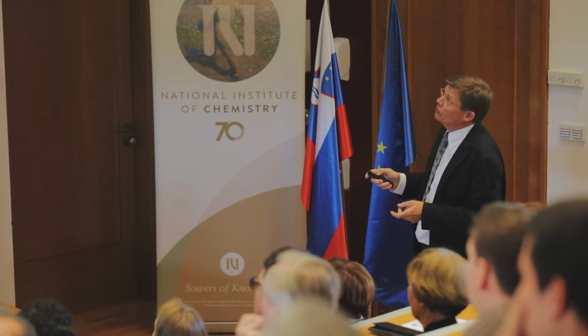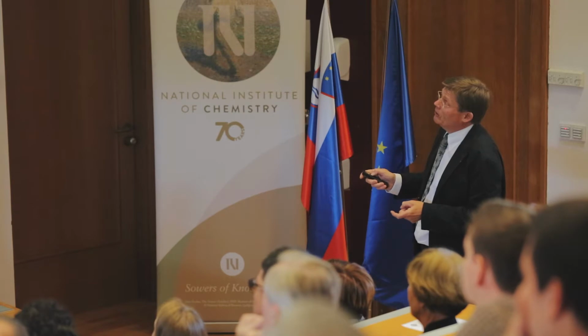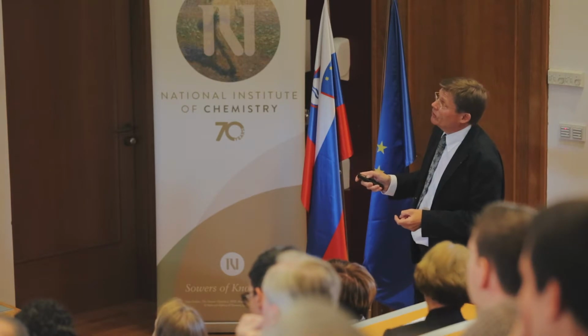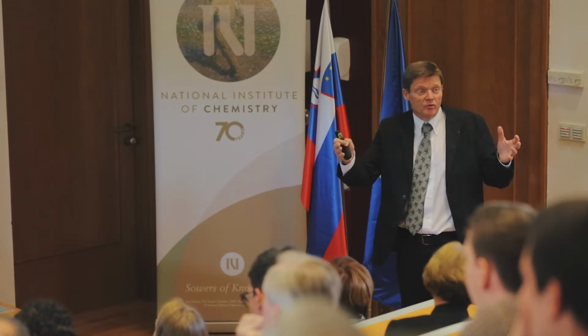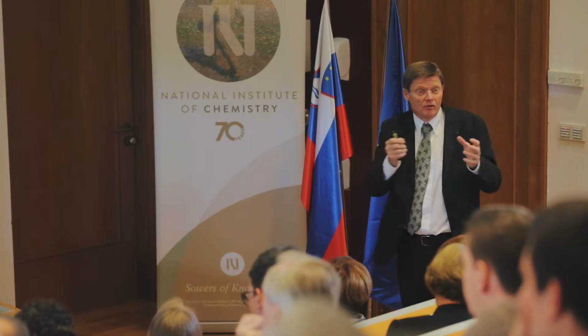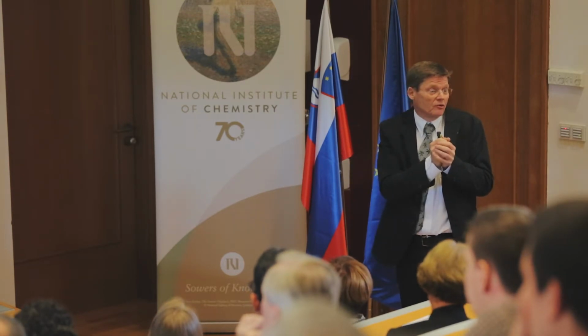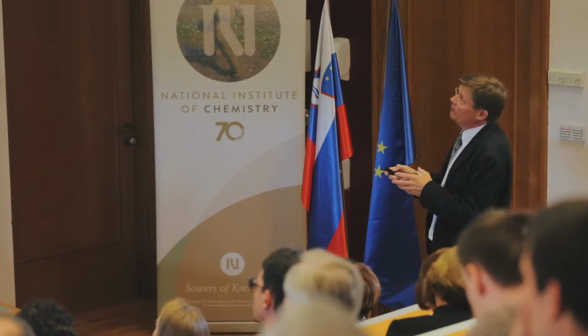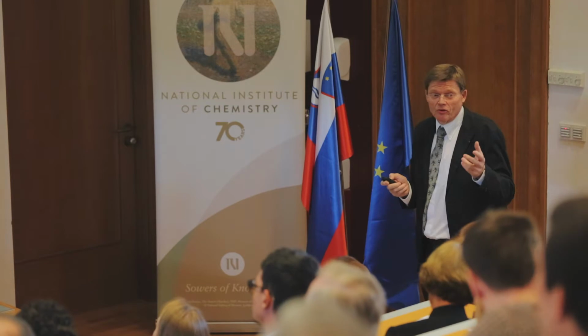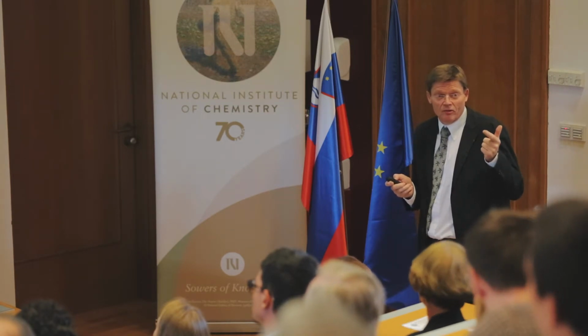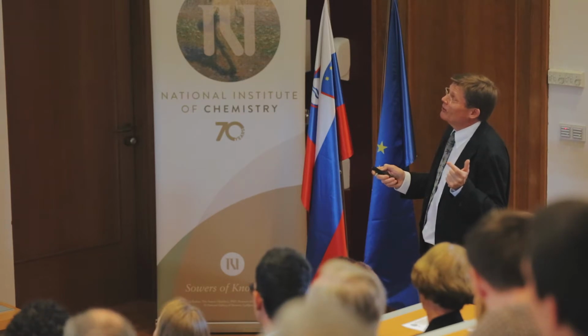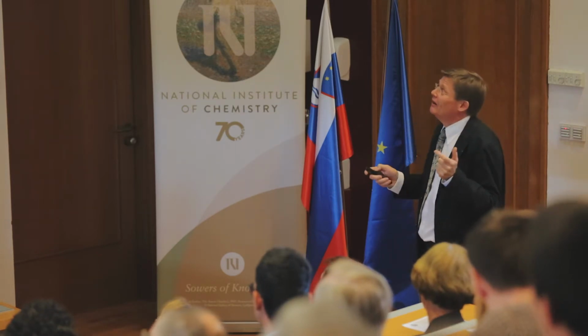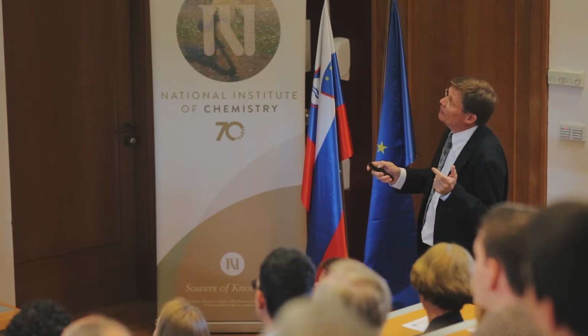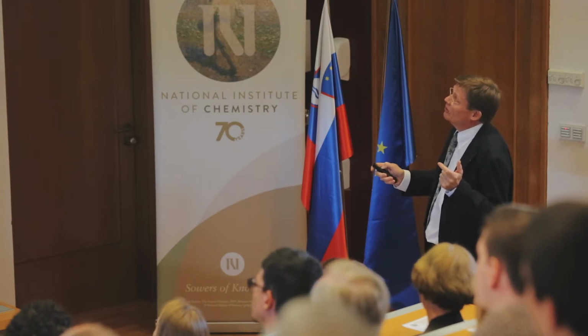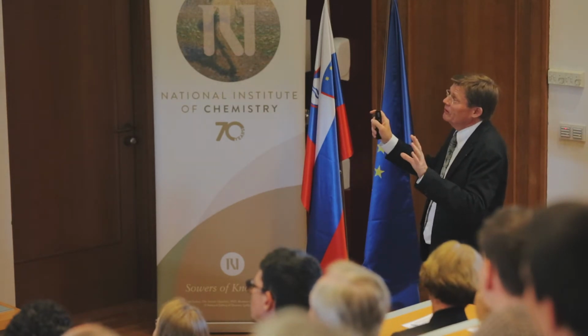On the other hand, from diffusion theory, it's known that the diffusion coefficient is inversely proportional to the time constant. And importantly, you have the size of your system squared. So when you have a large material, it takes very, very long, and a small one goes very quickly because it's a very sensitive dependence. The relaxation time can be formally written like normal circuits, like RC, resistor times capacitor. This gives a time constant. Now we take the chemical resistor and the chemical capacitor. The chemical resistor is obviously this, and the chemical capacitor is obviously that. So this is pretty clear.